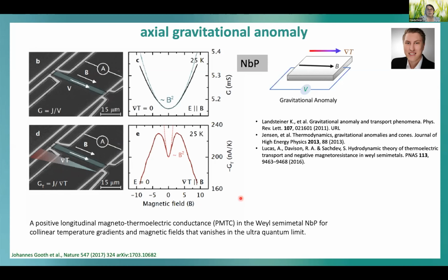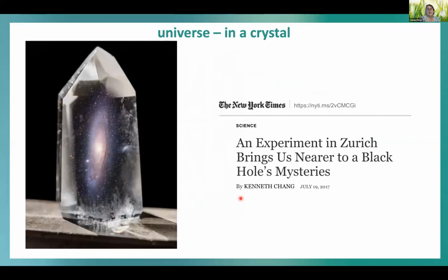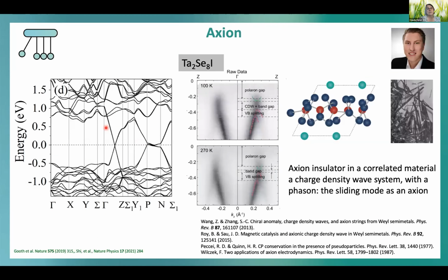So this was already very interesting. So we looked for more, and this brought us even into the New York Times. So we looked now for more nice Weyl semimetals, and on this way we found a very nice band structure of tantalum selenium 8 iodide.